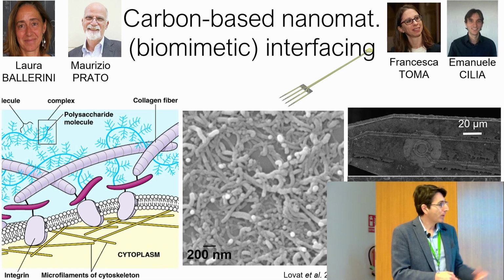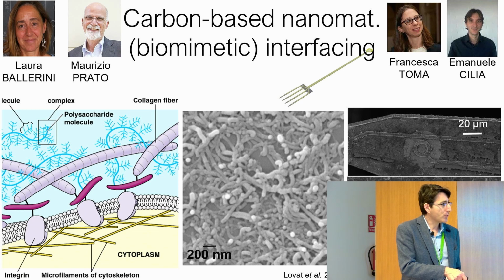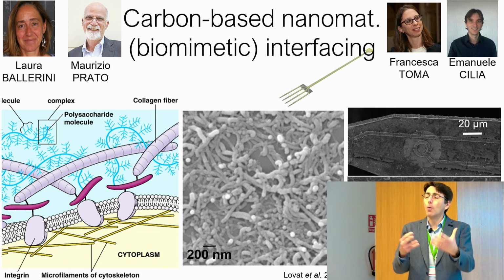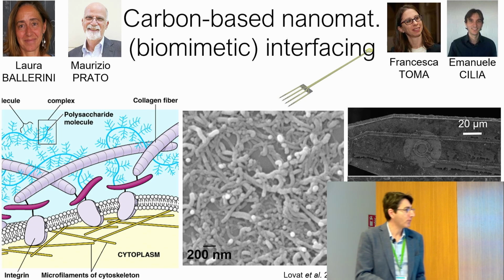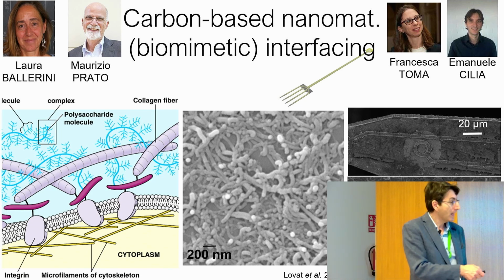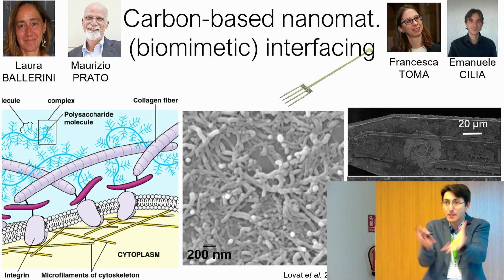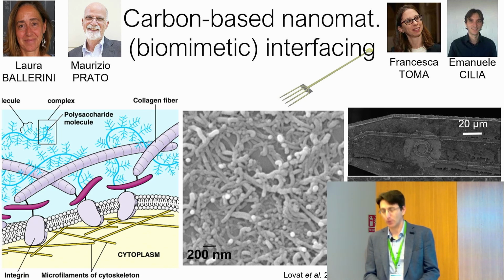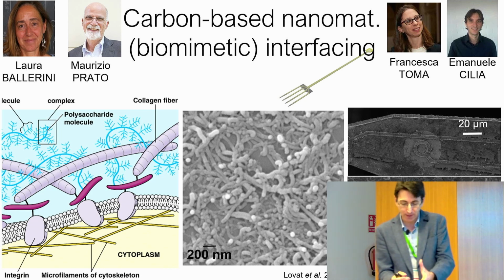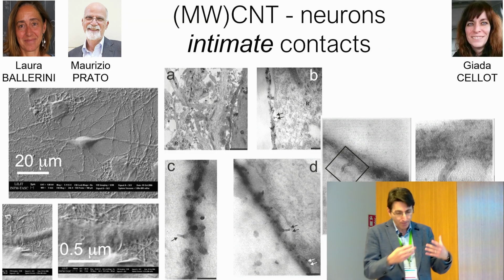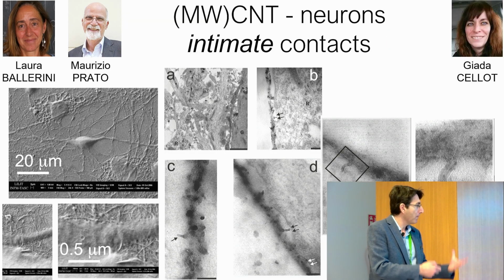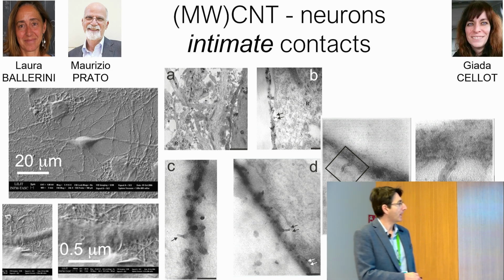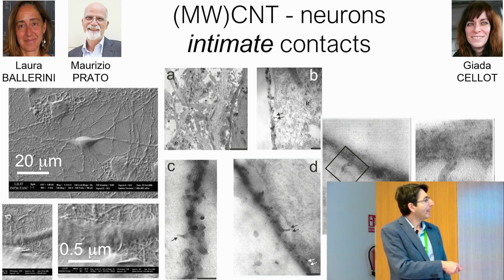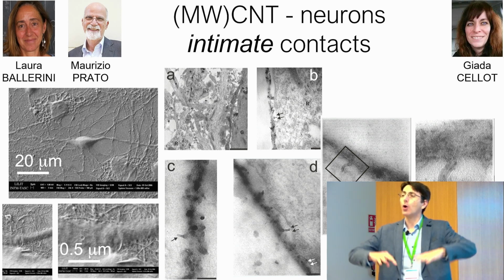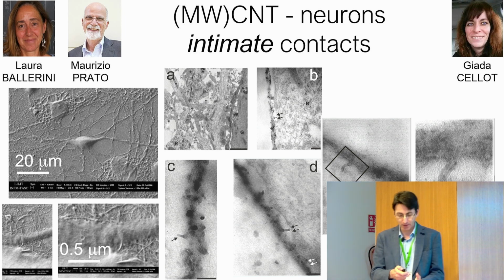What we actually did with two postdocs at the time was to devise a physical process to take the commercial silicon probes from NeuroNexus and coat them with these spaghetti meshworks of carbon nanotubes, just to make them more friendly for the tissue. But what was very interesting, found in collaboration with the lab of Laura Ballerini, was that not only do neurons love to sit on this spaghetti meshwork of carbon nanotubes, but also